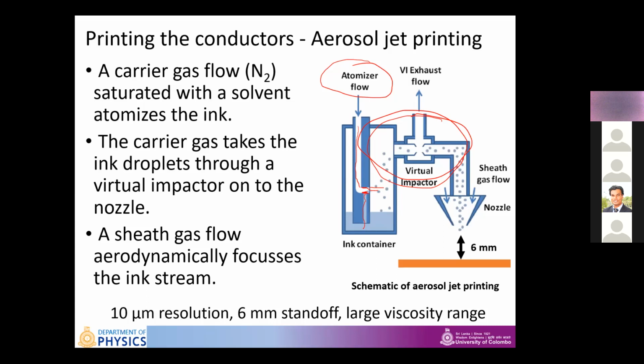Usually we can get down to about 10 micron resolution in best case. And also because this is about 6 millimeters up in air, it's not that sensitive to surface variations of the substrate. Therefore, it is ideal for printing electronics on paper substrate.